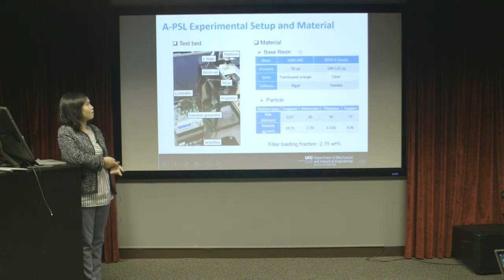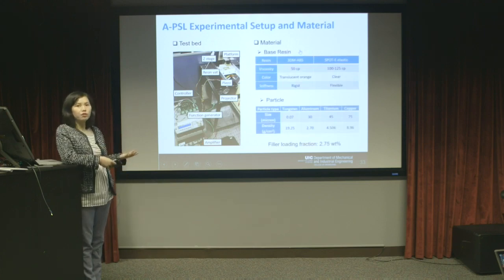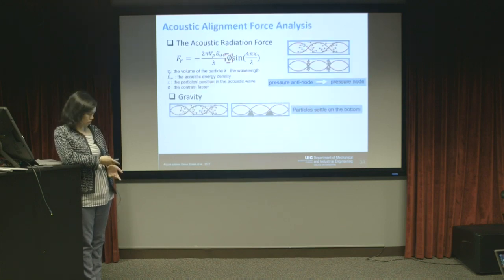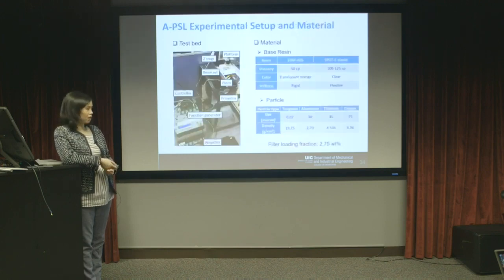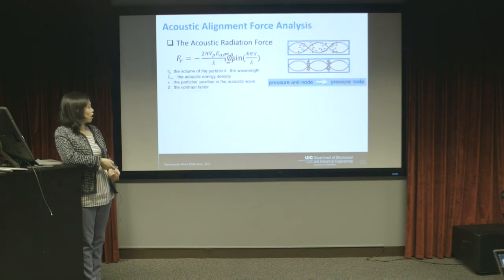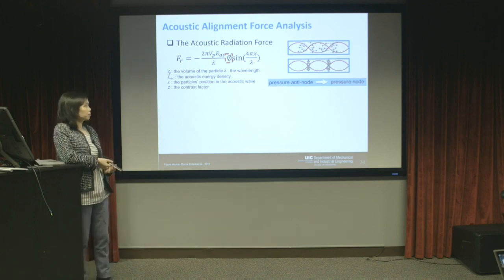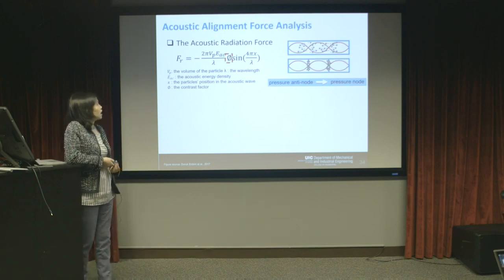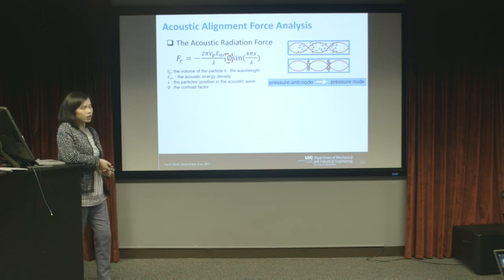Okay, we also built the platform, and we studied different liquid resins with different viscosities and different particles with sizes in a very large range, from 70 nanometers, like the tungsten particles, to about 100 microns, like the copper particles. And by the way, for the acoustic field assisted process, its limitation is the particle loading fraction. It's difficult to control suspensions with very high loading fractions. The loading fraction we tested is around 3% in weight ratio.